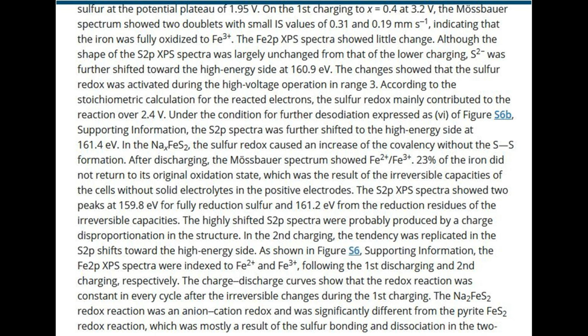After discharging, the Mossbauer spectrum showed Fe2+/Fe3+. 23% of the iron did not return to its original oxidation state, which was the result of the irreversible capacities of the cells without solid electrolytes in the positive electrodes. The S2p XPS spectra showed two peaks at 159.8 eV for fully reduced sulfur and 161.2 eV from the reduction residues of the irreversible capacities. The highly shifted S2p spectra were probably produced by a charge disproportionation in the structure.